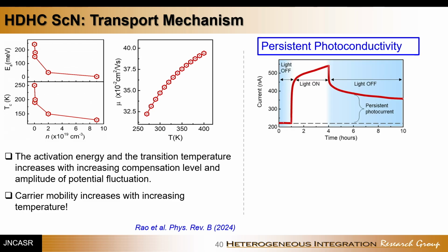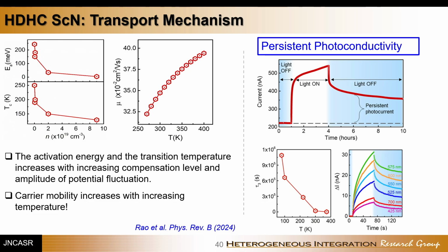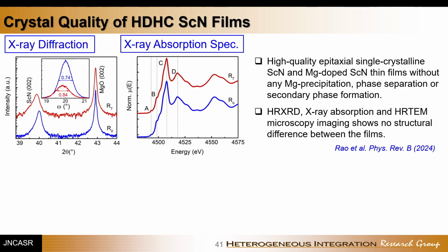The same thing about photoconductivity. So you shine light on this HC scandium nitride for some time, and then you leave it. In normal cases, you would expect the photoconductivity to drop in milliseconds or microseconds, or at least in seconds. Here you can see the photoconductivity just doesn't die. It keeps on going and on and on for 6-7 hours in the lab.